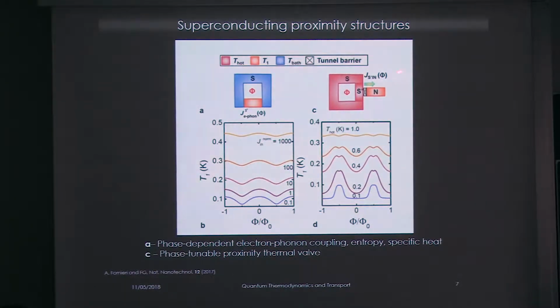And for instance, another possibility is to use this proximity part here. If we contact this proximity region, whose spectral properties can be controlled thanks to the flux, to an additional normal contact, in order to implement a sort of phase-tunable proximity thermal valve, no? Because the thermal conductance of this proximity metal, of course, depends, as I was saying, on the phase, and so the thermal transport between this S prime and N becomes fully phase dependent.